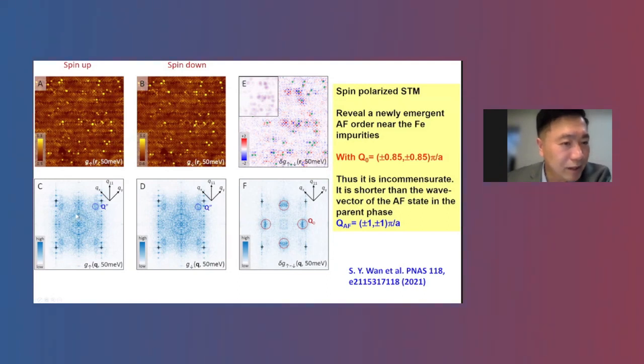No, I don't think this is real. It's a Fourier transform of this single spin-resolved mapping topography. I think it's due to a Fourier transform effect. You can see this spot here, which looks like it comes from the tungsten tip. Actually, the one-quarter-one spot does not show up strongly, but here there was a spot. And you mean this arc? Yeah, that one. I was curious whether you think that's real or an artifact. That's not a true effect. I think it's induced on this picture by the Fourier transform for some reason. Okay, thank you. Thank you. Any other questions?